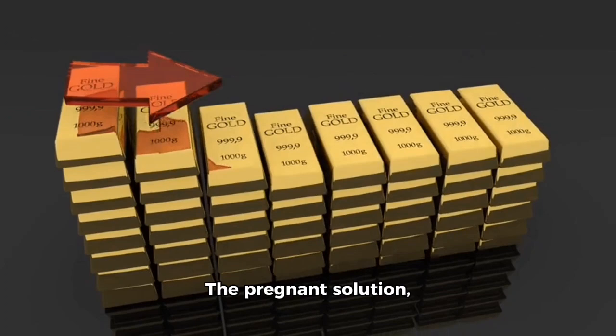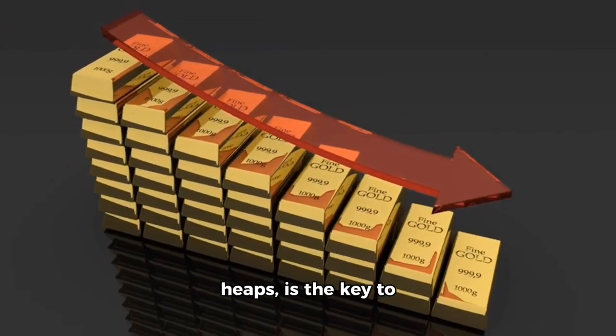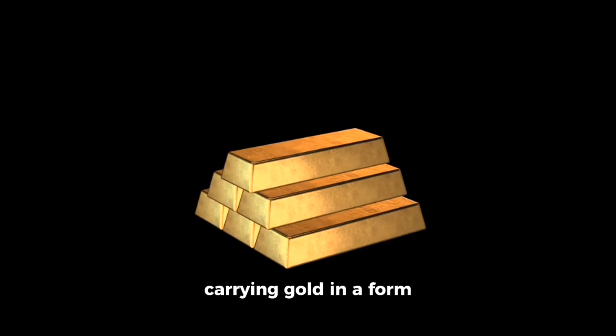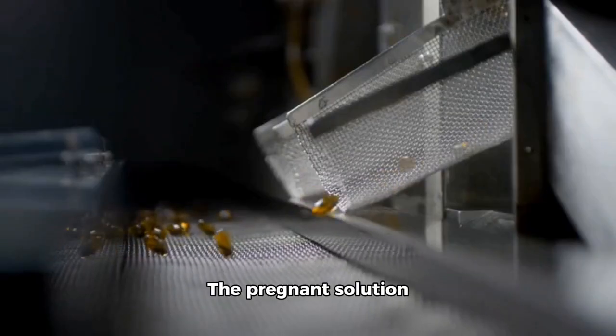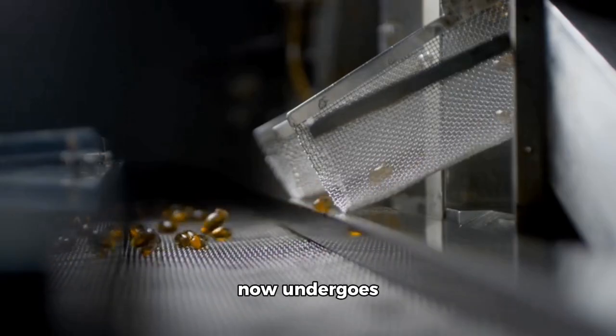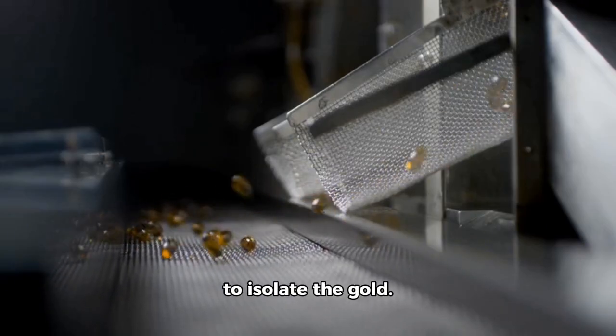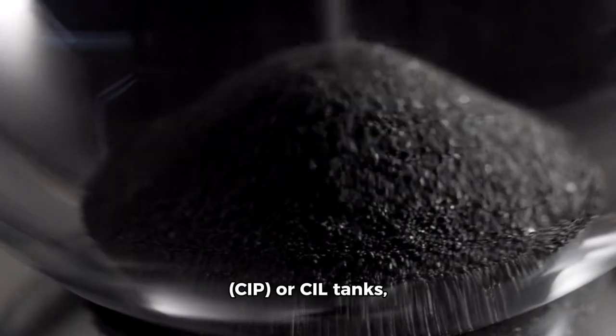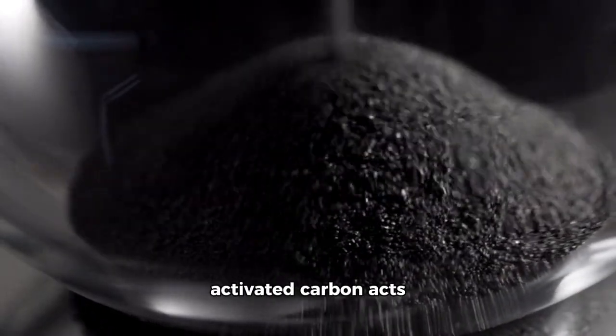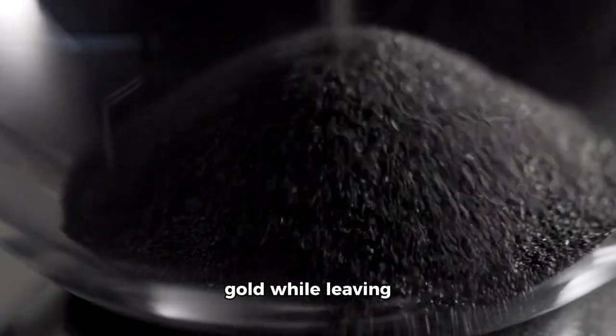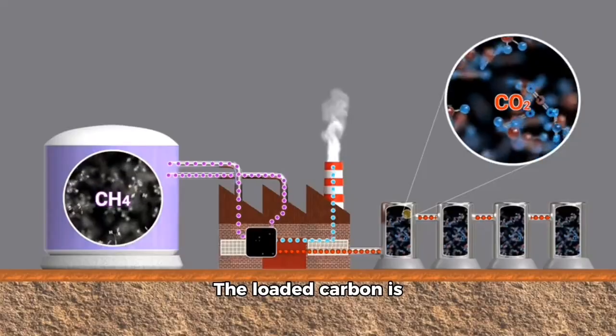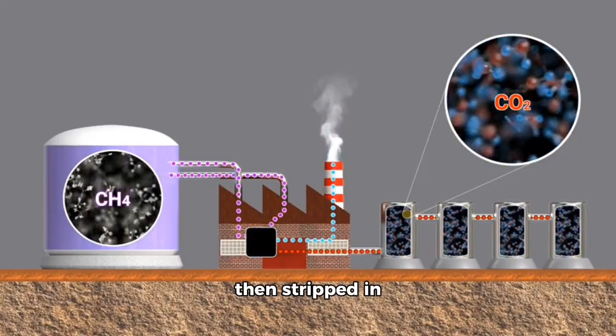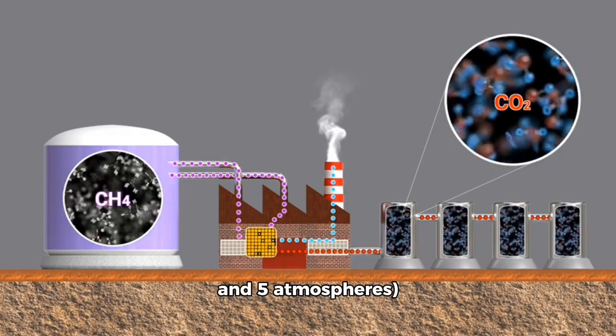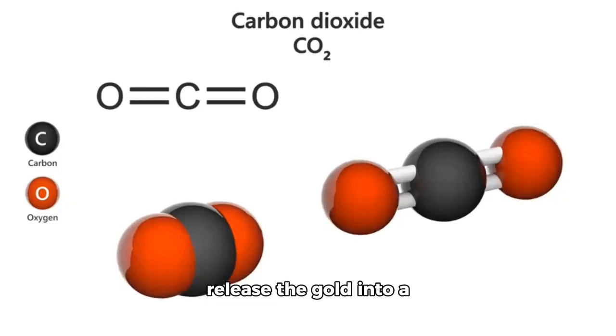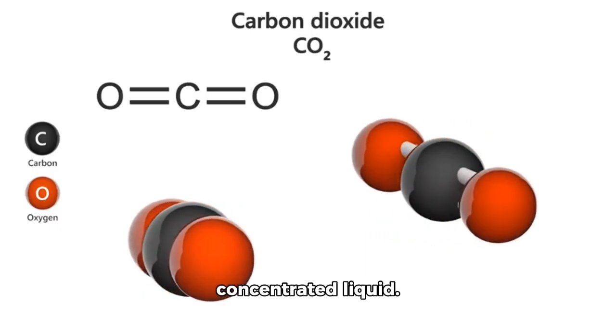The pregnant solution, whether from tanks or heaps, is the key to the next phase, carrying gold in a form ready for capture. The pregnant solution now undergoes adsorption and elution to isolate the gold. In carbon-in-pulp, CIP, or CIL tanks, activated carbon acts like a sponge, binding gold while leaving impurities behind. The loaded carbon is then stripped in elution tanks, where high-pressure solutions up to 150 degrees Celsius and 5 atmospheres release the gold into a concentrated liquid.